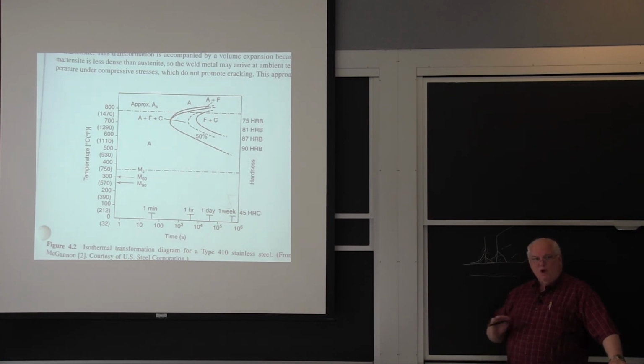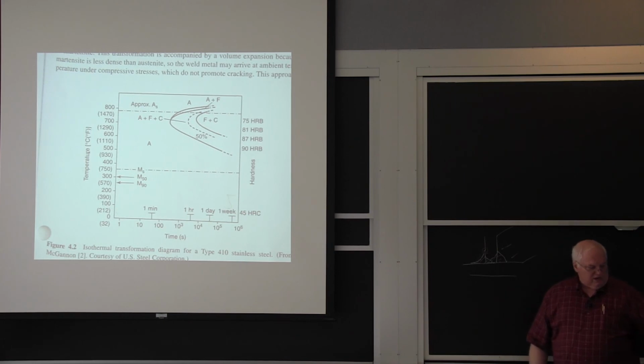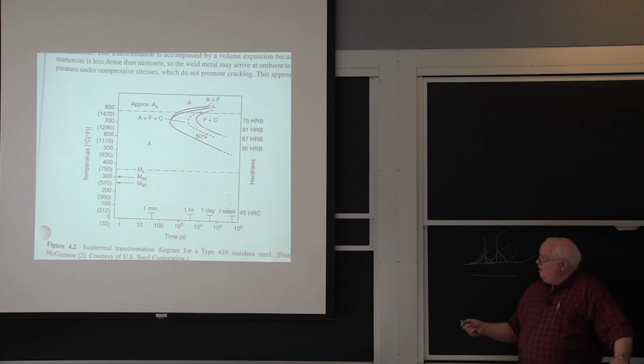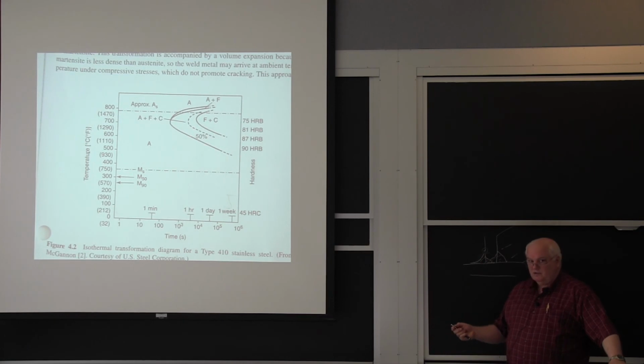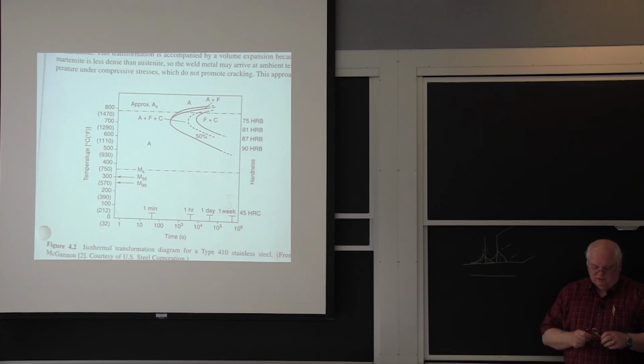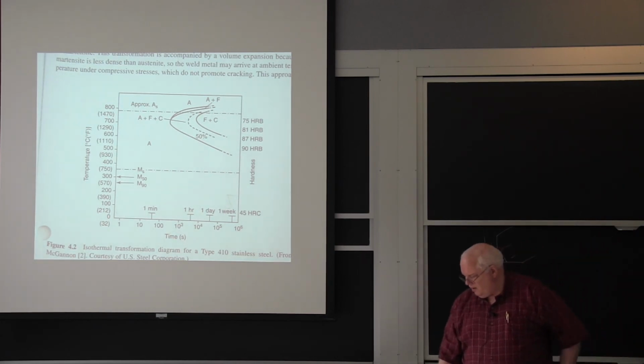So it doesn't matter what you do with one of these types of steels, when you weld it, you're going to get martensite. Unless you weld it and then put it in a furnace and slow cool it over about a day or a week. Okay? This stuff is really hardenable, very high hardenability. With 12% chromium, it has extreme hardenability, which means it's very, very difficult to weld. Okay? That's not to say we don't weld it. We do weld it, but we have to be careful about how we weld it. And it's susceptible to hydrogen cracking.